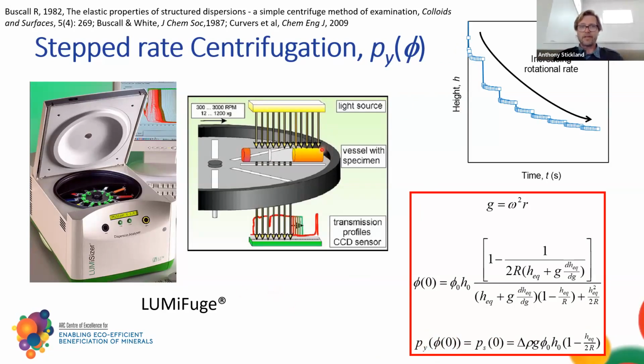The only issue with this is that the manufacturers only make tubes with a centimetre diameter, and we did a whole lot of work for over about 10 years to show that actually they're too small. The wall effects are all too significant. So we've kind of gotten rid of this technique, except for the most extreme cases. This works well for nanoparticles, for example, because they never sediment under gravity.